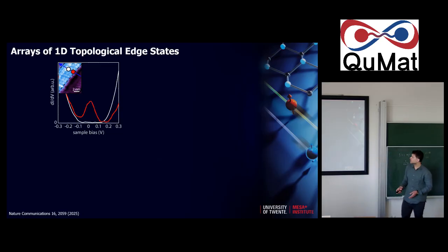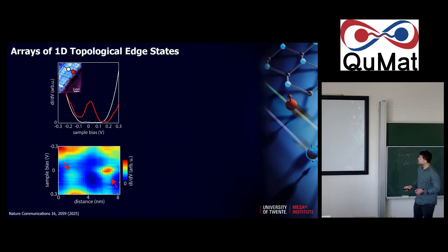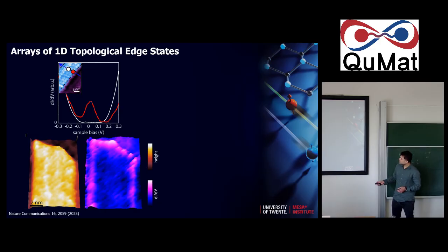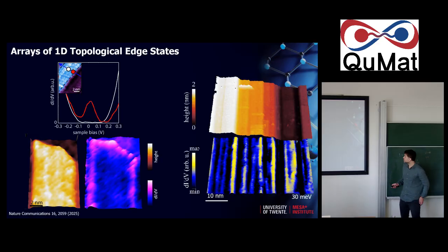So we took again a nanoribbon over here, and we looked at the edge and in the middle of the nanoribbon. And again, you see that in the middle, it has this gap-like feature, while at the same energy range at the edge of the nanoribbon, you have this pronounced state. So again, we have this edge-bulk correspondence, and you can even map both sides, and you see that both sides are metallic with a pronounced state. You can even map the whole nanoribbon. So there's another example here where you have a nanoribbon that terminates, and you see that the end state is just running around the whole ribbon, just like in the case of the 2D flake.